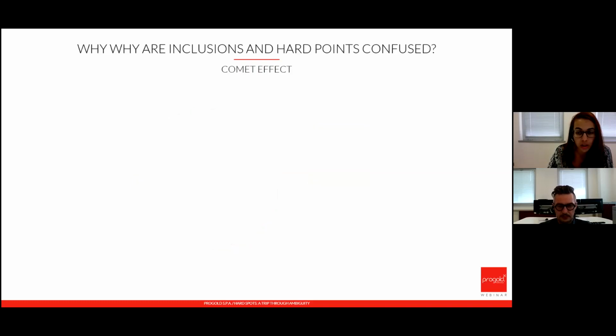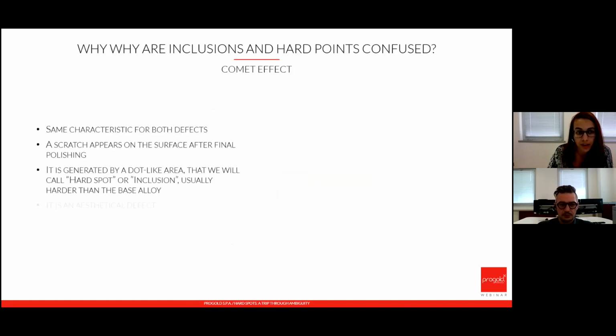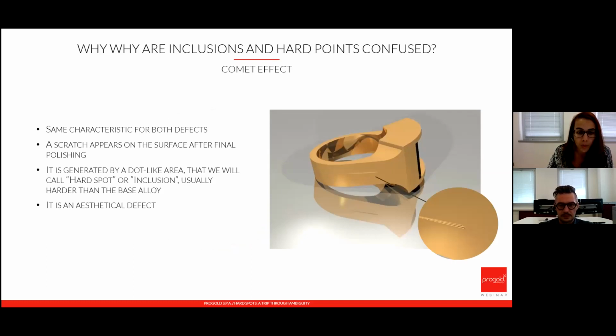However, they are usually confused together because they share a common characteristic, which is called the comet effect. What is the comet effect? This is something that appears at the end after we have polished, and it is an aesthetical effect. What we have is an inclusion that is harder than the base material that we're polishing. So when the brushes come over the surface, they're pushing this inclusion, and it's just like a boulder on wet mud. When we are pushing it, the boulder is just taking with it all the material in front of it, leaving behind a streak that is empty. This comet, as I said, is typical for both inclusions and hard spots, but the fact that we do not have it does not mean that we do not have the problem.